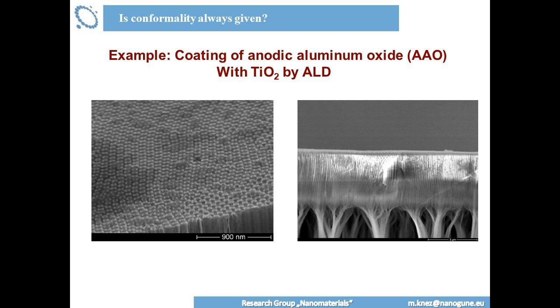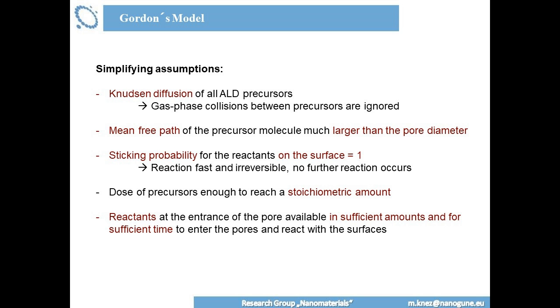And in agreement with that, you need also to select appropriate dosing times. That means appropriate amounts for dosing the precursors. That's really, really essential, because if you don't have enough precursor, you will never reach proper surface coverage. And for this here, also the reactants at the pore entrance are available in sufficient amounts and so on. So this is, I think, all you need in order to make a model as easy as possible and understandable.